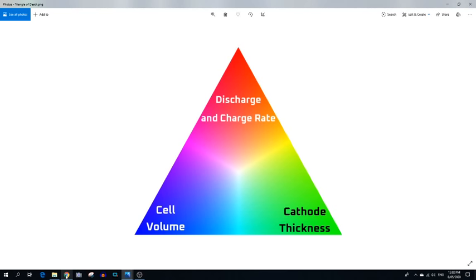Now, I said that there were two ways to shrink the triangle to try to fix all these things at once. The first was Maxwell's dry cell technology, which uses a lot less additive material, and because the additive material isn't being corroded by the liquid solvent, it has much lower resistance. Because it has much lower resistance, electrons can get in and out of the cell much more quickly, and there's less heat. The other way to combat it is to improve the thermal management system of the battery. So that's the problem we're trying to solve.